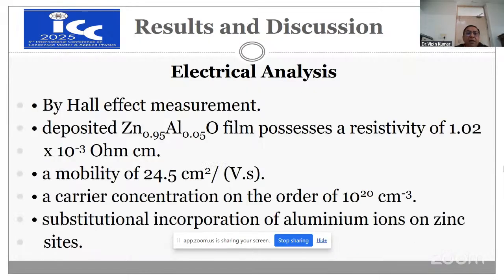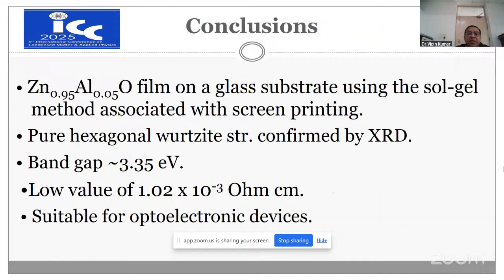Electrical analysis. By Hall effect measurement, the deposited film possesses a resistivity of 1.02 × 10⁻³ ohm-centimeter, a mobility of 24.5 centimeter square per volt-second, a carrier concentration on the order of 10²⁰ centimeter⁻³, indicating substitutional incorporation of aluminum ions on the zinc sites.